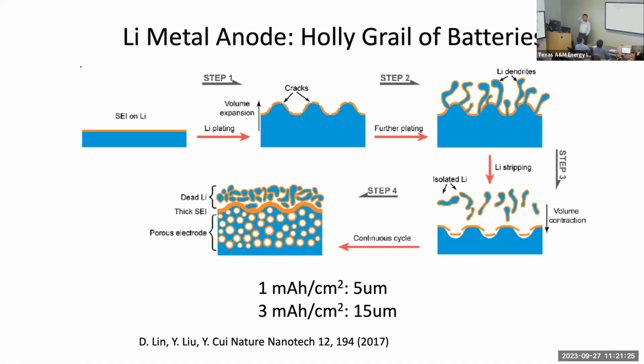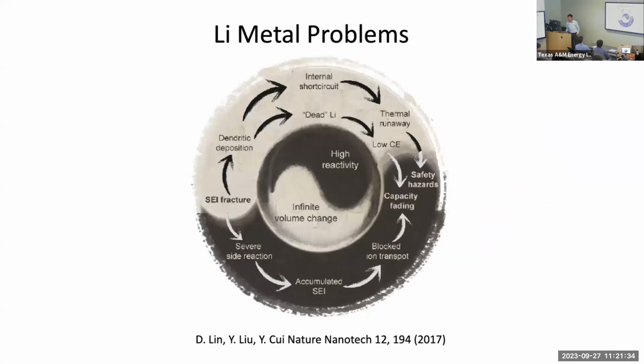Deposition will expand. When you do discharge, it's going to shrink. The lithium metal cell cannot handle that. So there are so many problems coupled together. And when dendrite formation causes shorting and all these surrounding phenomena, what I truly believe is if you want to solve the problem, you've got to identify the root causes. And the middle two are the root causes.